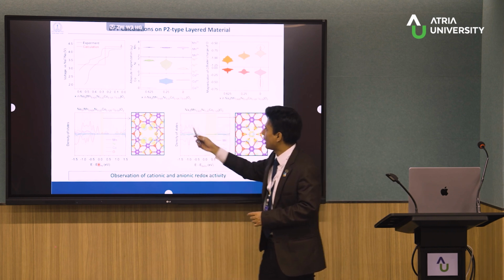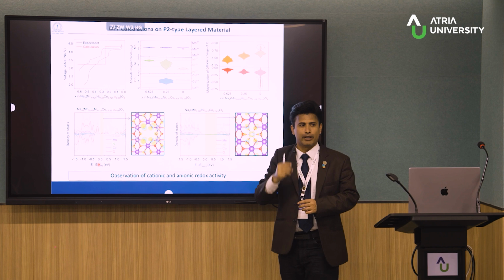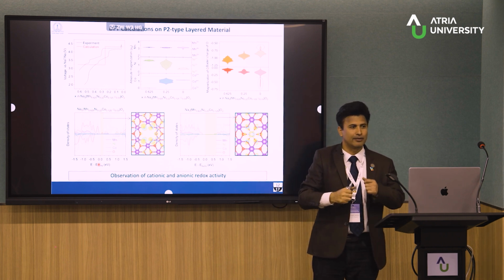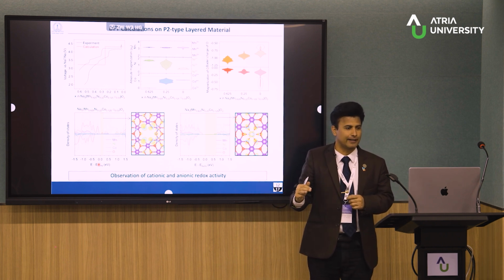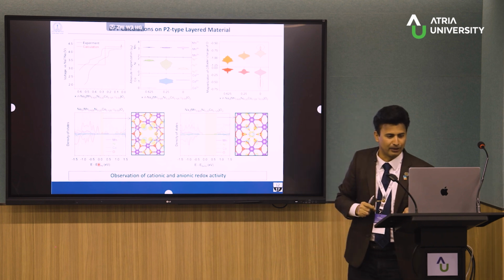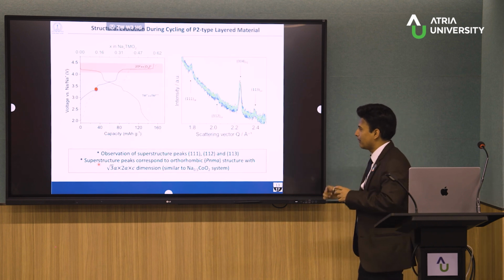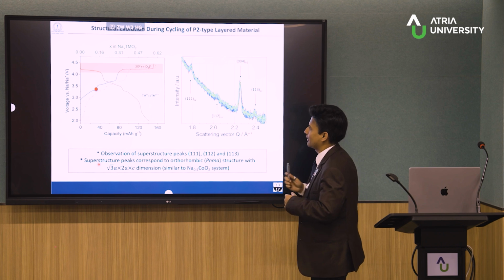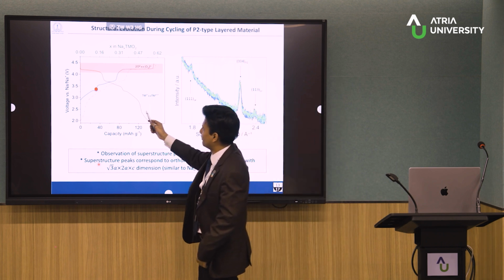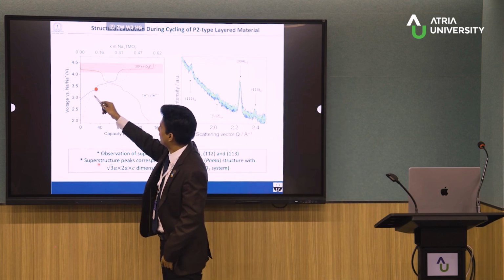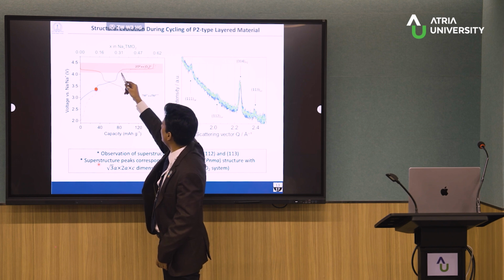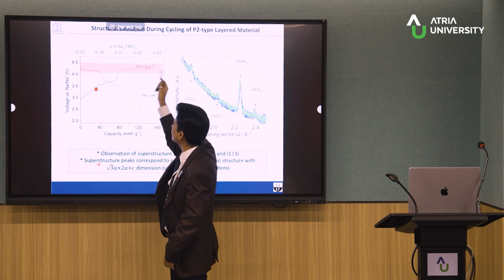Now one reason why we put cobalt 10% is because cobalt is known to give some structural stability and cycling stability. That's the reason why we are putting a small amount. Okay, now coming back to even more crystallography study. So this is our typical voltage profile with low voltage cationic, mostly nickel, and high voltage anionic redox.